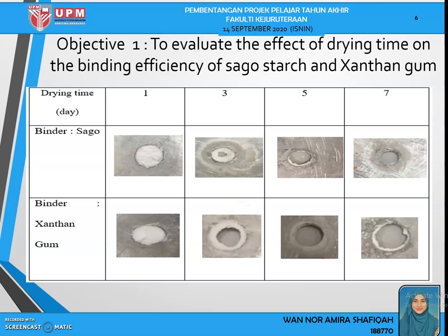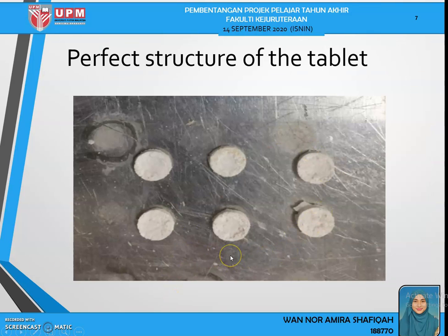For example, for a tablet collected after day 3, it can be noticed that there is still some left over, about 50% attached to the mold for the BG tablet prepared using both binders. The BG tablet bound using xanthan gum seems to be much drier and thus has less mass attached to the mold. This indicates that the xanthan gum dried much faster compared to the sago starch. The sago starch completely dried in 7 days, but the xanthan only takes 5 days. So this is the perfect structure of the tablet, and it is used for the second objective.